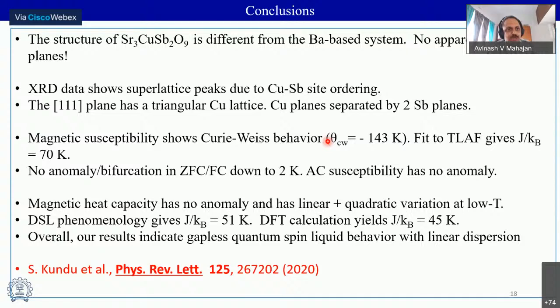So with this, I'll just put up the conclusion slide where we have looked at strontium copper antimony oxide, which is found to be different from the barium-based system in that the structure is different and apparently has no triangular planes. However, because of the Cu-Sb site ordering, one does see triangular planes if one considers the 111 pseudo-cubic. In the pseudo-cubic cell, if one looks at the 111 plane, one does see a triangular lattice. And based on various bulk and local probes, there is a clear evidence of the absence of a long-range order.